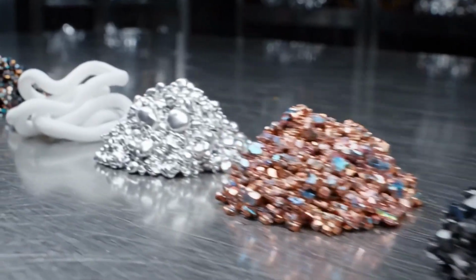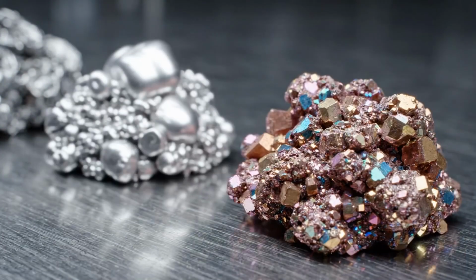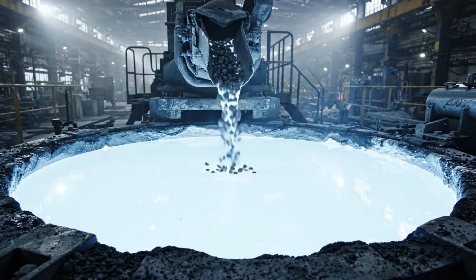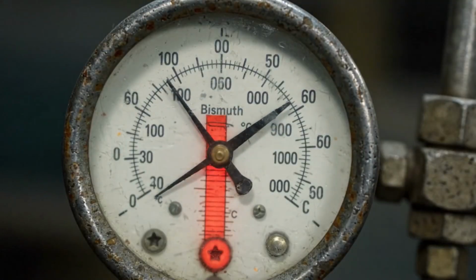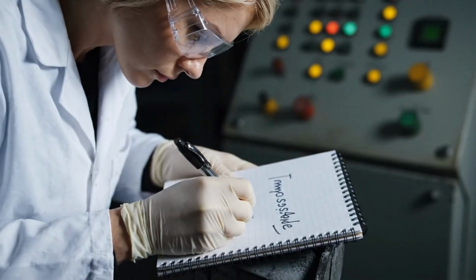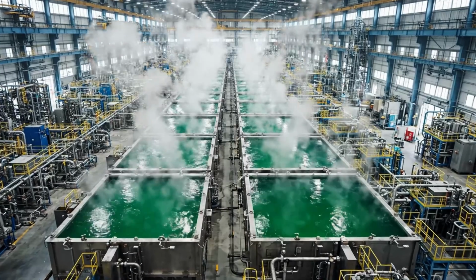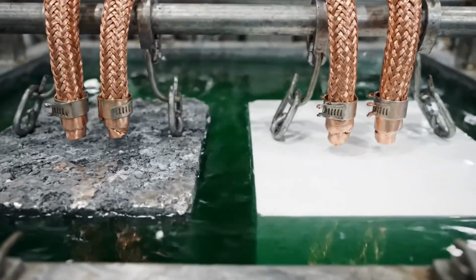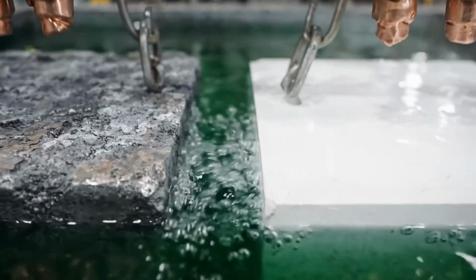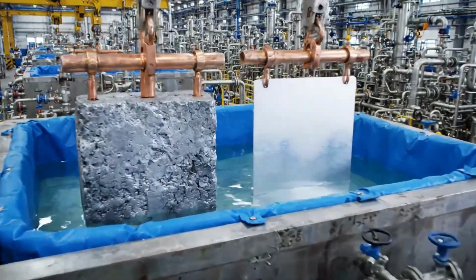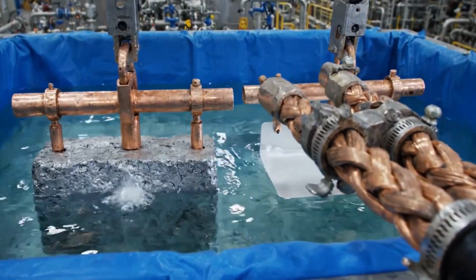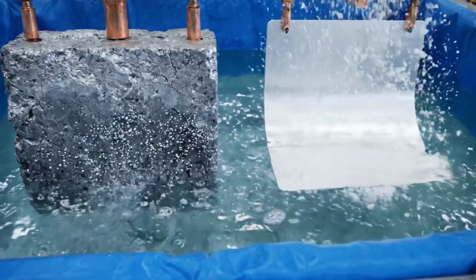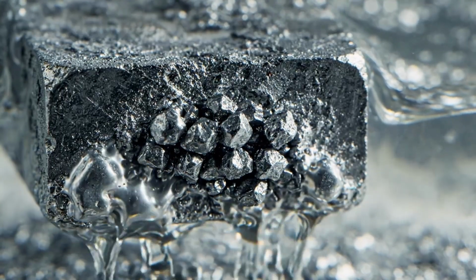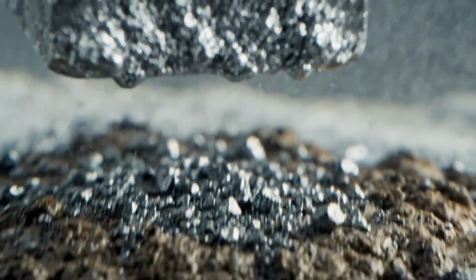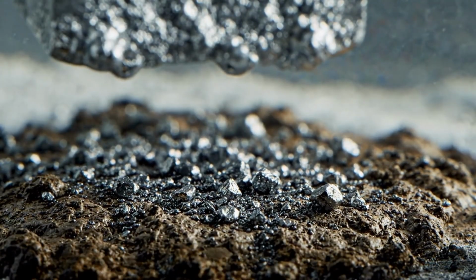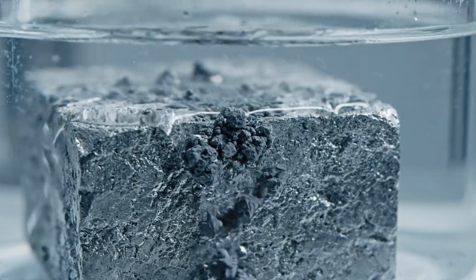The last relevant impurity is bismuth, whose separation from lead by pyrometallurgical means is chemically impossible. The two metals are too similar. To remove bismuth, the Betts process is used, an electrolytic refining method of extraordinary elegance. Impure lead acts as the anode and is slowly dissolved in a lead fluorosilicate electrolyte. Simultaneously, on the cathode, pure lead is deposited atom by atom, layer upon layer, with a purity exceeding 99.99%. Bismuth and other residual impurities are trapped in the anode as a dark sludge that is recovered and processed. An X-ray fluorescence spectrometer certifies the final result with atomic accuracy.